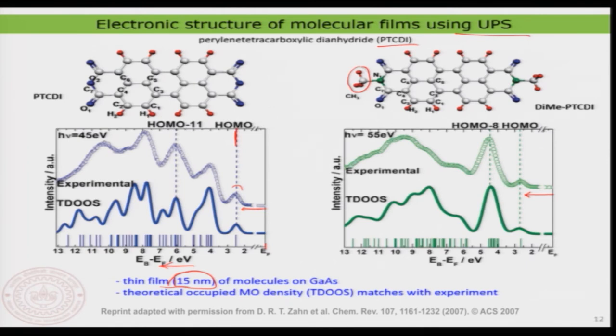What you are also seeing here is the theoretical calculation to make a comparison, and it nicely matches with the density of state of the molecule. These are the discrete levels. These lines tell the discrete HOMO, HOMO minus 1 and so on, and this plot here is the density of state itself. That means you are plotting how many electronic states are present in a given window of energy. You can see here there is no state between 3 and 2, there is one state, and between 4 and 5 I have about 8 or 9 states, for example. That is how you calculate the density of state.